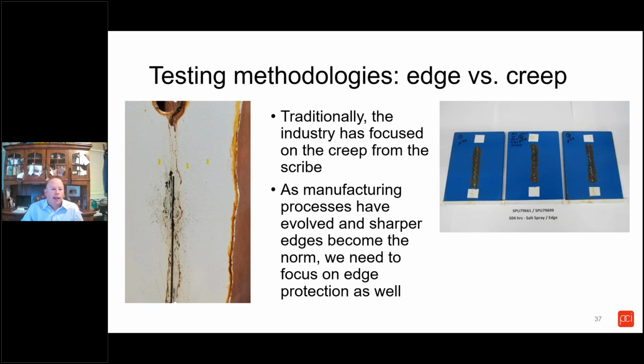Salt spray has been the traditional method of testing, and it's usually evaluated as creep from the scribe, a line cut down to the substrate, or an X, then measuring the scribe from that.